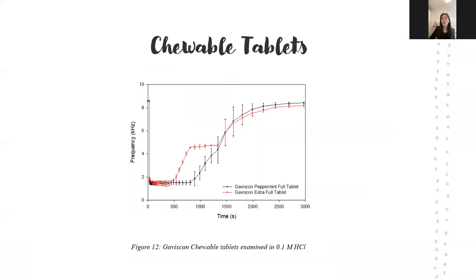So we're just going to look at one form of this, which is Gaviscon, and it was analysed in 0.1 M HCl. Samples were only analysed in tablet form as the powder were found not to be wettable in the aqueous solution. And just to note that extended time frame at 3,000 seconds, 50 minutes, as opposed to the 600 seconds of a time frame we've seen previously. So both formulations are sugar-free and contain similar excipients. The difference in active ingredients is expected to contribute to the profile of these.